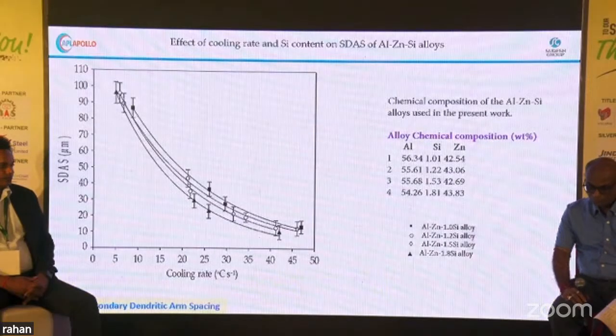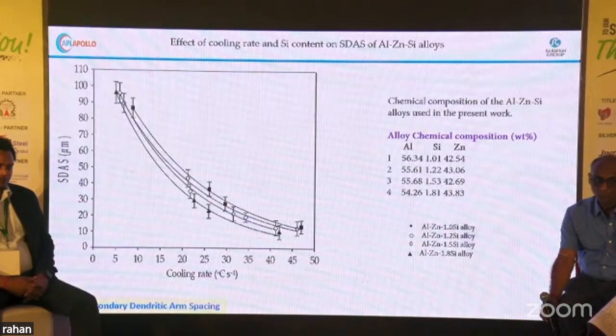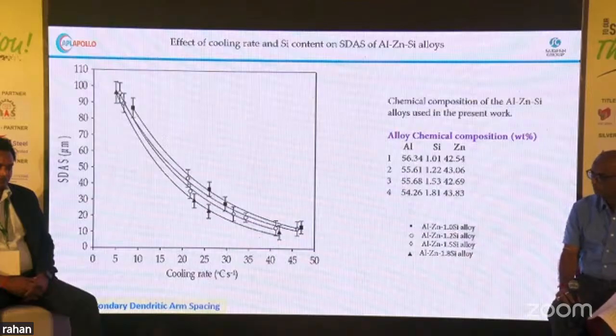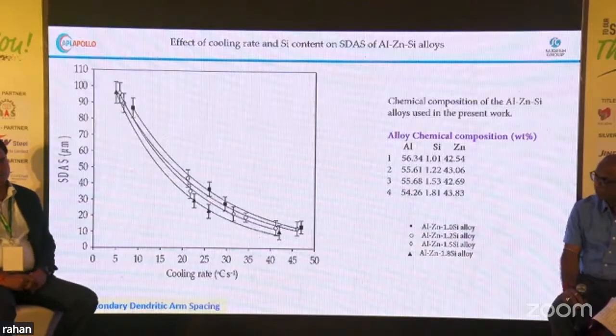Why is 1.5% silicon there? We can see here 1.0% up to 1.8% silicon. Up to 1.5% silicon, with cooling rate up to 20 or 25 degrees Celsius per second, the slope of the secondary dendritic arm spacing is very high. After that, when we increase the silicon content, the slope is decreasing. So that's why, in 55% aluminium, 43.5% zinc and 1.5% silicon is chosen.